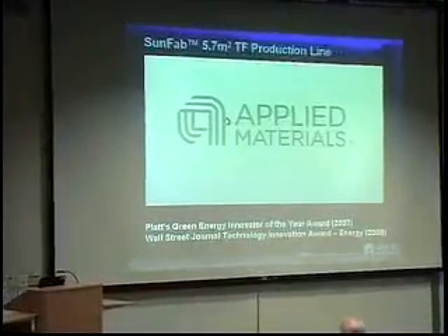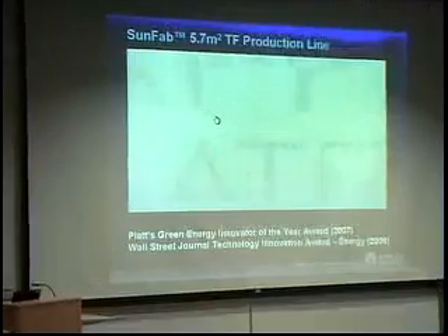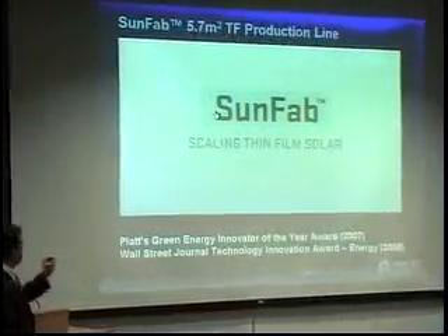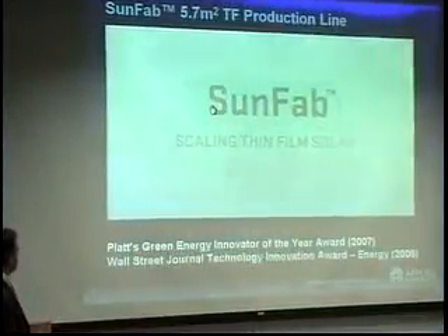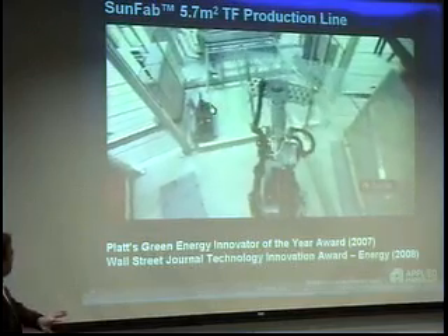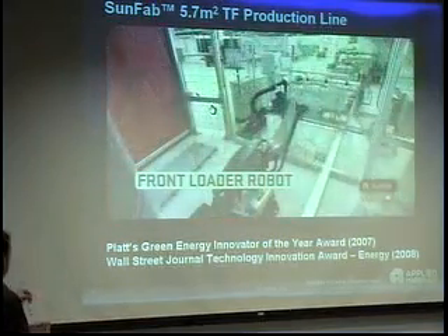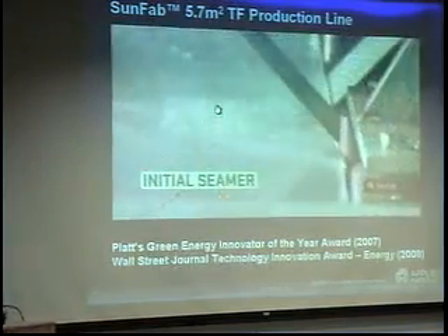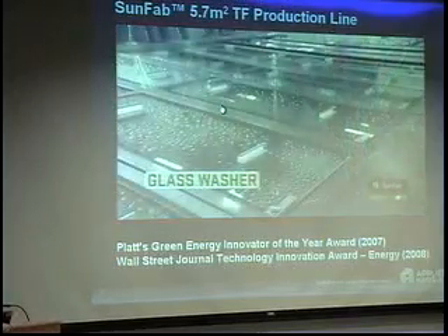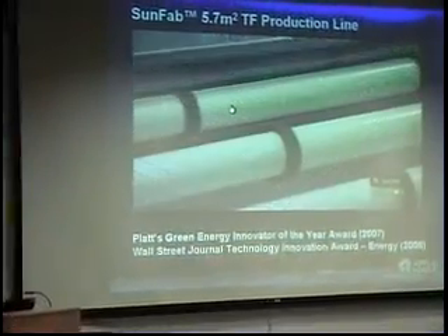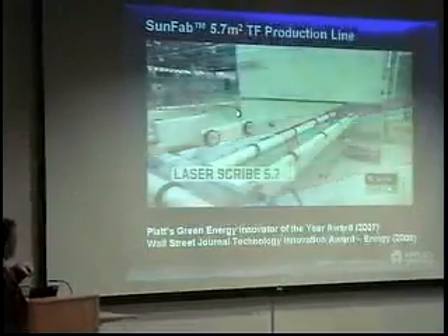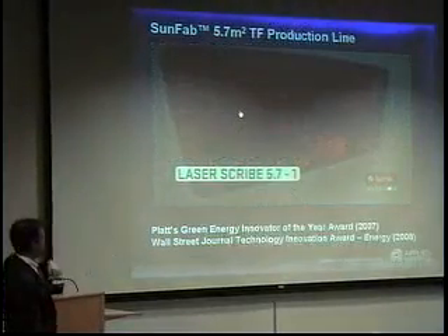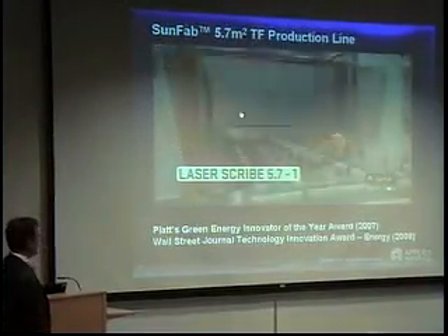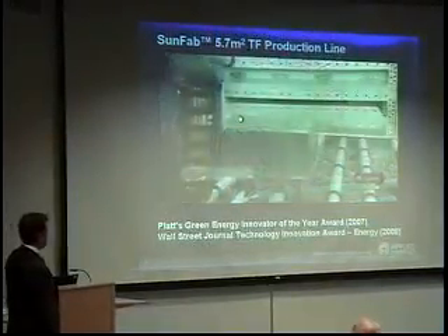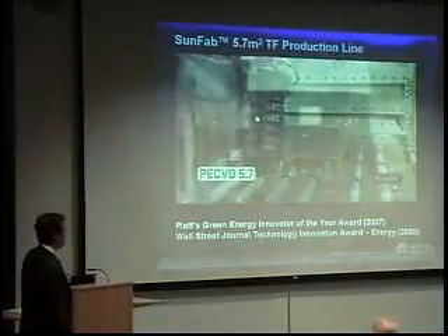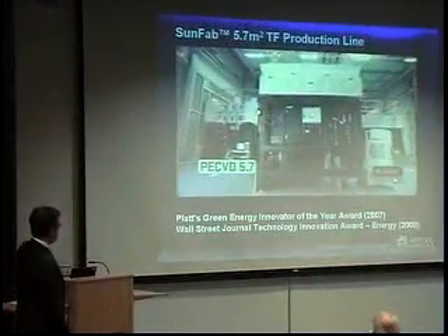So in this case, the glass is going to come in coated with a TCO, transparent conducting oxide. Remember, that's the thing that lets light in but still acts as a conductor. So we pull it from the glass company out of a box with a robot, put it into the line. We clean off the edges, clean off the top and bottom. Now we're going to put it in what's known as a laser scribe that's going to pattern the transparent conductor. Comes out of there, goes into the big CVD system to put the silicon on. And there's that big machine again.